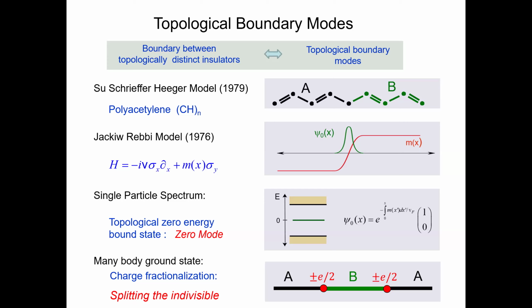So what this charge fractionalization does in real polyacetylene is it changes the relationship between the charge and the spin of the particle. Normally, if you have a spin one-half fermion, a charge e goes with a spin of h bar over 2. Whereas here you can have a charge 0 with a spin of h bar over 2, and a charge e with spin 0.